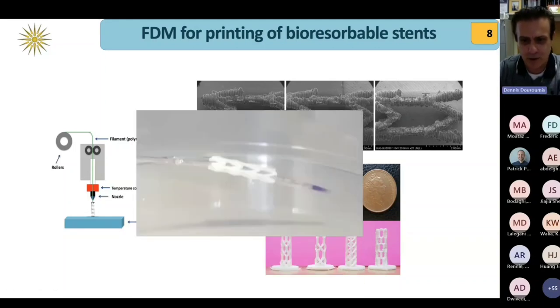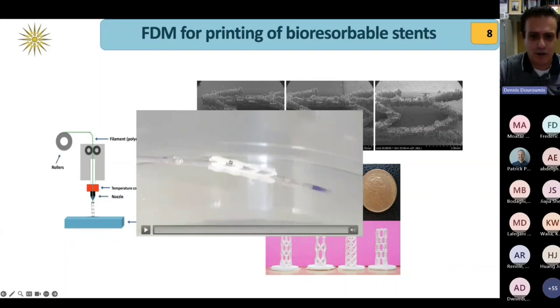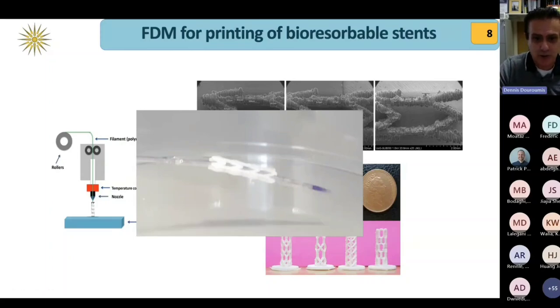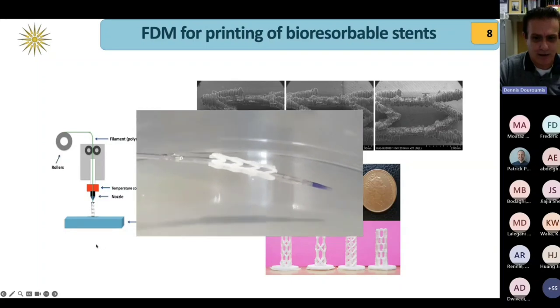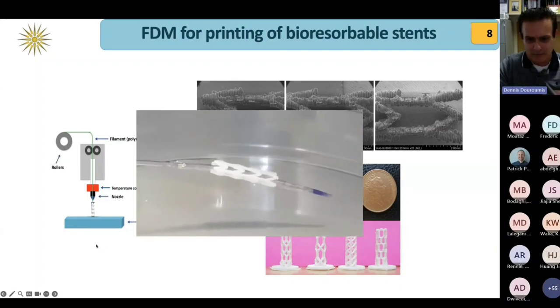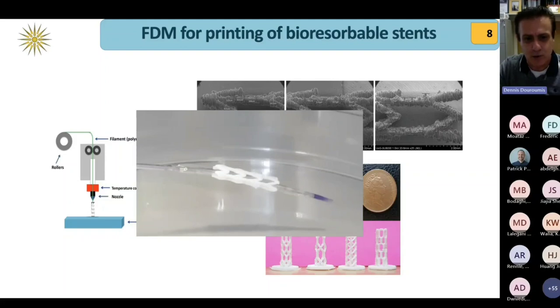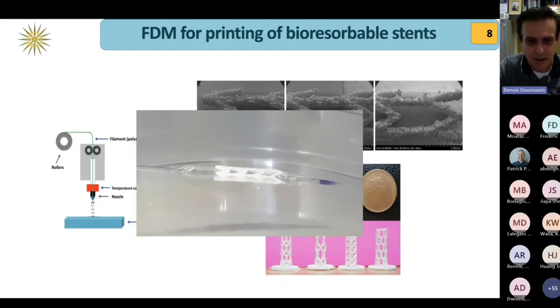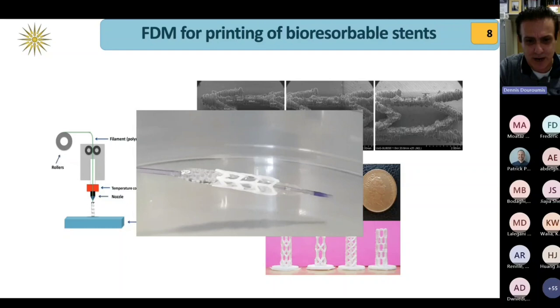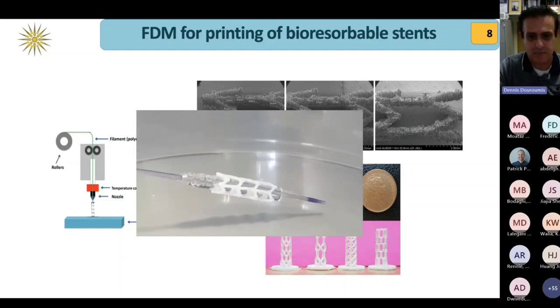However, one of the things was that we managed, by using certain combinations of these materials, to make 3D printed stents by FDM, crimp them on a balloon, and then try to expand the balloon and simulate the process and see if the stent is going to withstand the crimping and the expansion. And you can see a video clip that we ran that was quite good. Further evaluation showed that the stent was quite robust and it didn't break. We didn't have any defects after the expansion in balloon angioplasty.